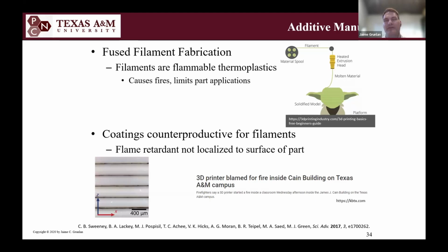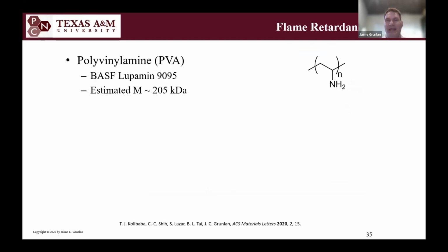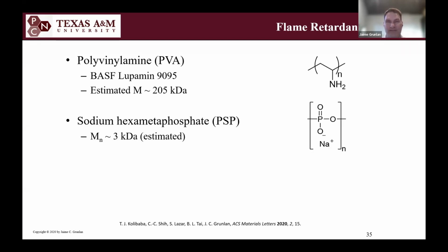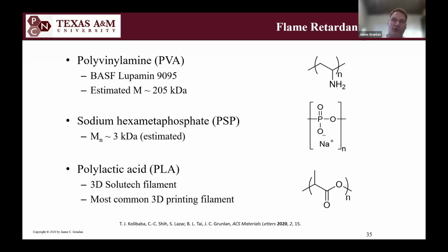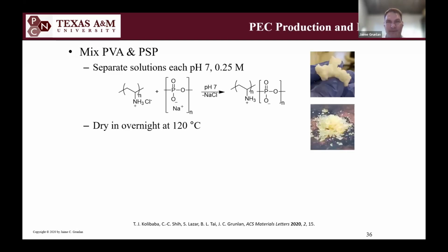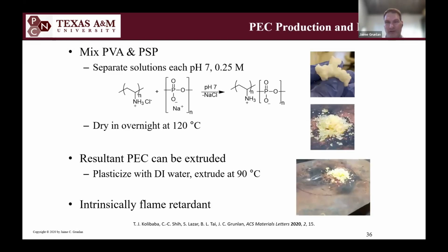And so we wanted to see, could we use these polyelectrolyte complexes in a completely different way? We wanted to make it an additive to a 3D printing filament. So we took polyvinyl amine, a different nitrogen-rich polymer, and that same PSP I had used previously that I told you about. Then we dried a polyelectrolyte complex and made a powder, and then we mixed it into polylactic acid to make 3D printing filament. This is just the PEC that you're looking at here.